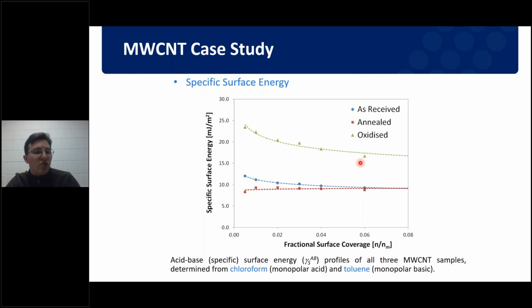So the oxidized sample now has that much higher specific surface energy. The introduction of those highly polar groups, those high electron density groups, have made it much more polar on its surface and increased the elution times that my polar probes would have had as they were passing through my column and passing over my sample. And we can see the annealing has had the opposite effect. It has reduced the specific surface energy.